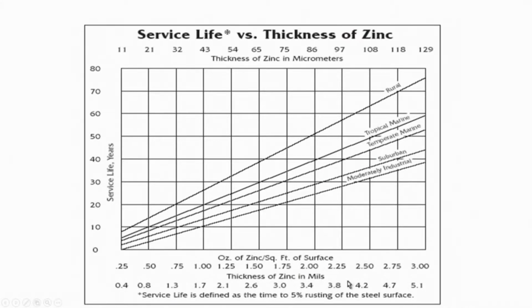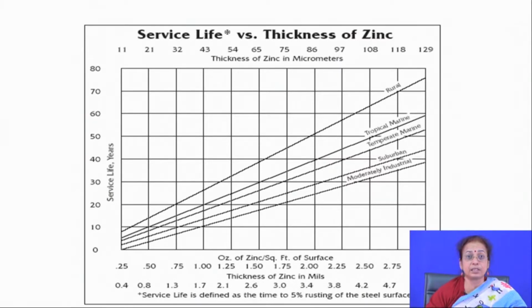If you go on increasing the thickness from 0.25 mils to 3 mils, or you can say from 10 micron to 120, 130 micron, the service life increases from about 1 year to as high as 80 years. So, thickness of zinc is very important. Apart from all the parallel techniques available for zinc deposition, hot dip galvanizing offers the maximum thickness on the surface with a strong interface.